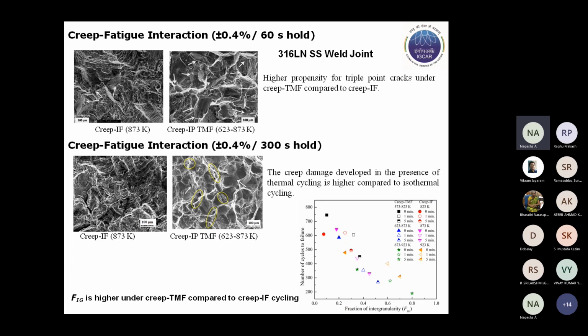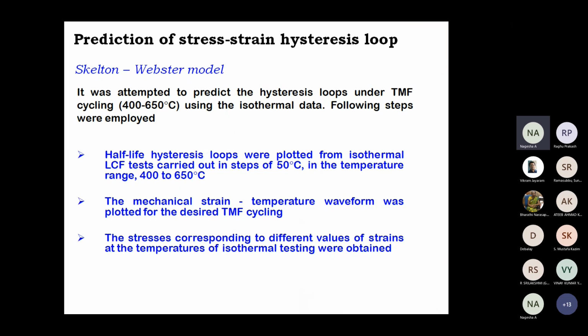And we have examined the fraction of intergranularity, which was seen to be consistently higher in the case of creep TMF compared to creep isothermal cycling. Similar exercises have been done, though I have not shown them, in the case of continuous cycling also, wherein similar observations were made. And I will just give a brief outline of the modeling of the hysteresis loops which we have attempted.